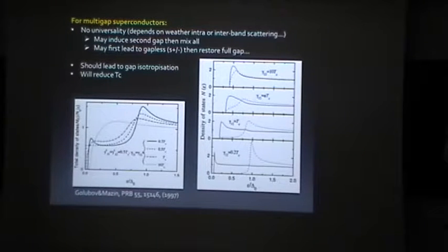But I believe the nice feature is that you can start from one system, a single crystal, and with the very same sample you create defects in a controlled way. You can add more and more, and you can even remove them by annealing the system. So I believe it's one of the best ways to introduce defects in a controlled way, where you know where you start. You don't solve everything, but at least it's not like comparing different samples that are already doped and pristine samples that are different. So this is, I think, experimentally the technique which is the most appealing for me.